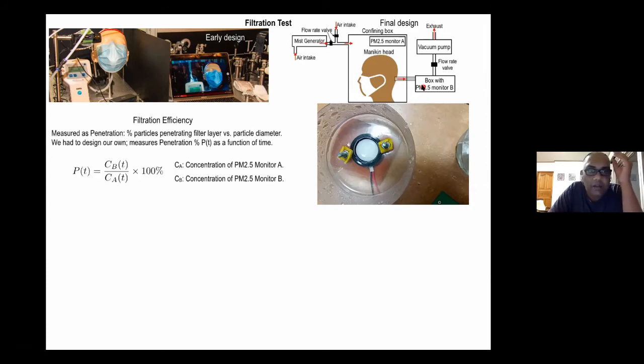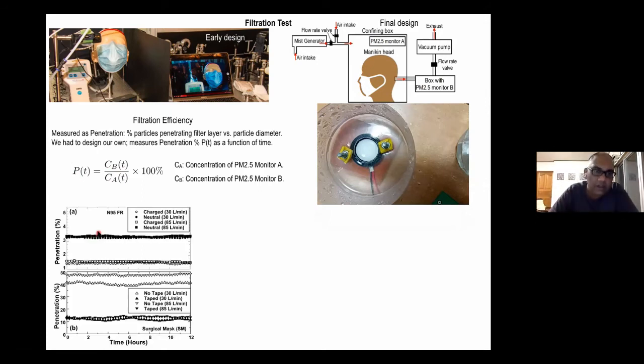This was homemade, but the filtration efficiency is usually defined as the penetration, which is the percentage of particles that have penetrated through the filter layer, and it is usually quoted versus the particle diameter. But since this PM2.5 monitor only tells you the micrograms per meter cubed of particles going through, it does not tell you what diameter of particles you are detecting. So instead, we took a time series of the concentration for monitor B divided by concentration for monitor A times 100%. That gives me the penetration, and we did it at 15-minute intervals over 12 hours. Here I'm showing you the data. This top plot shows penetration as a function of time over 12 hours at 15-minute intervals.